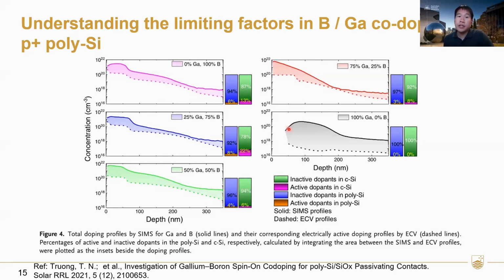But if we look at the SIMS here, we see that the actual physical concentration of gallium is much higher. It means that there's actually a lot of gallium, and indeed, this inactive gallium has been used by other groups, who managed to activate it using pulse lasers to achieve good contact with gallium doping.